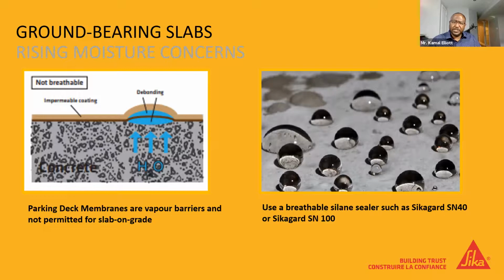you're susceptible to the effect of that rising moisture, bringing solubles up and popping off your coating. So if you tried to put a conventional deck membrane coating system, or even a conventional epoxy or polyurethane down on a slab on ground, and you're 2, 3, 4 levels below ground in an underground parking garage, you really do open yourself up to that potential for blistering and failure of the coating because it's impermeable. So the conventional wisdom, and what you'll see in S413, is that you need to make sure that your ground slab has some sort of breathable treatment, not an impermeable treatment.